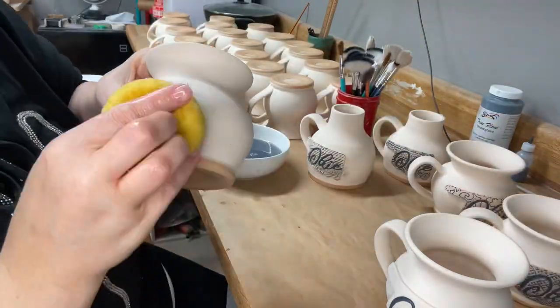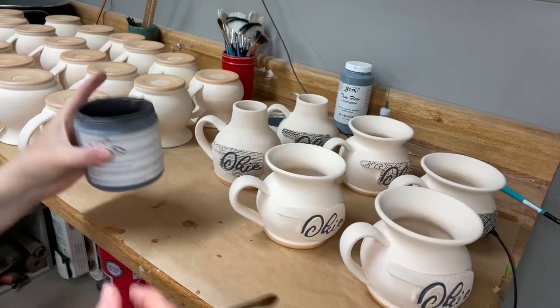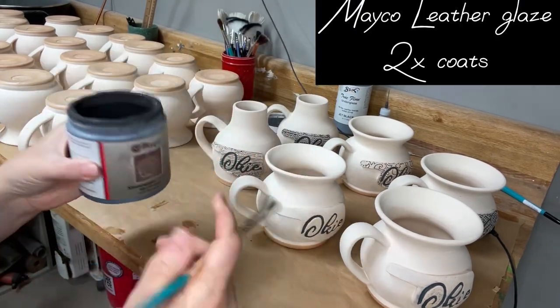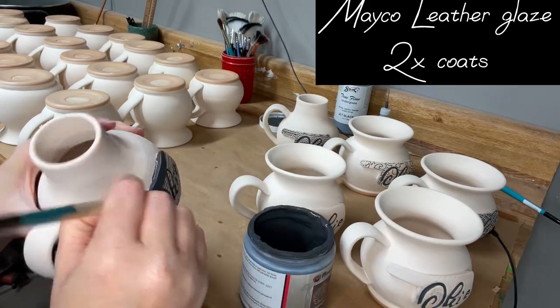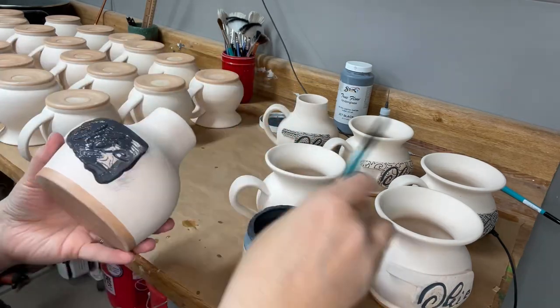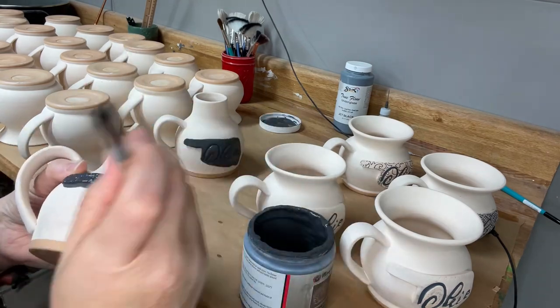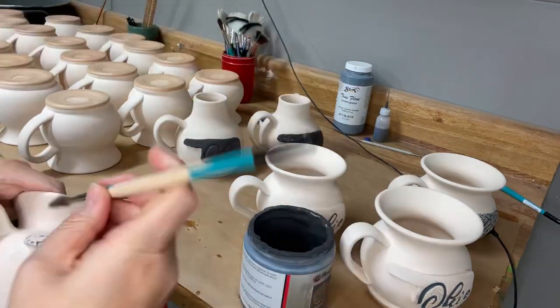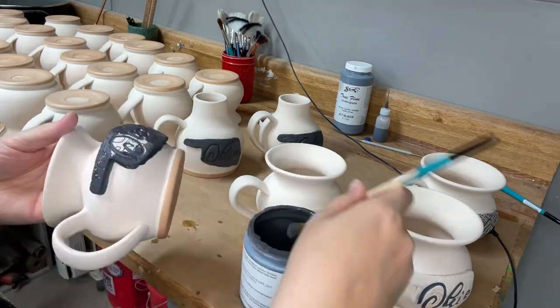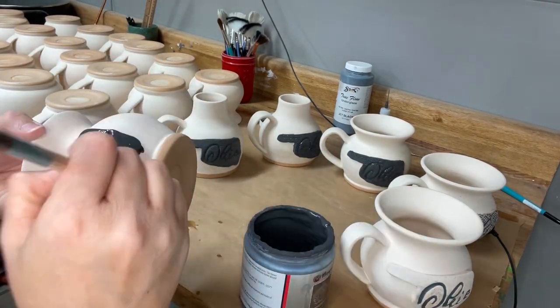That western texture rolling pin is probably one of my favorites. Now I'm putting glaze over the top of those decals and over the underglaze — that's Mayco Leather, two coats. I do one thick coat around the edges and inside all of the detail making sure to get into all the crevices. On the second coat I lightly brush the glaze over the top to just hit the high points. With Leather, the thinner the application the darker it is, so hitting just the high points on that second coat makes the raised portions lighter and it ends up looking really cool.